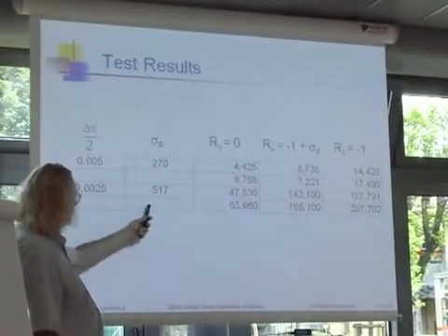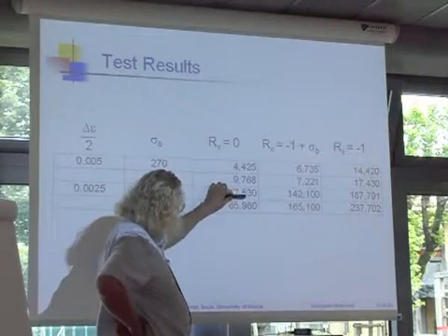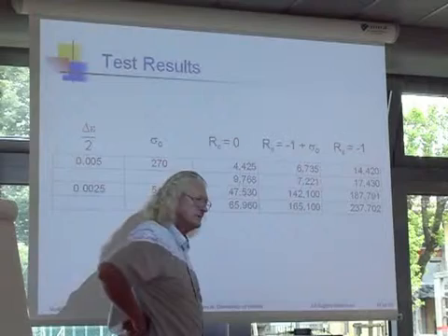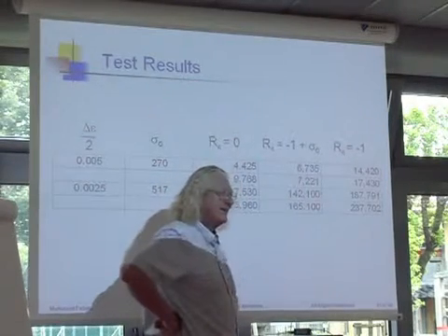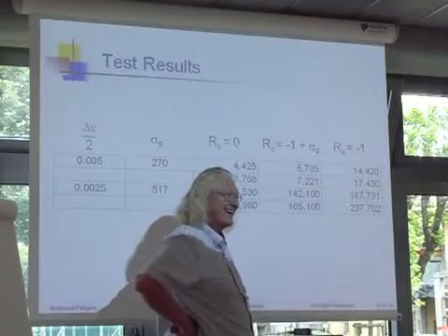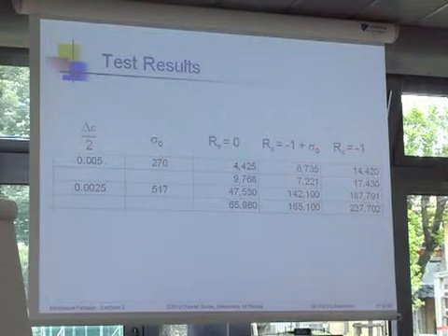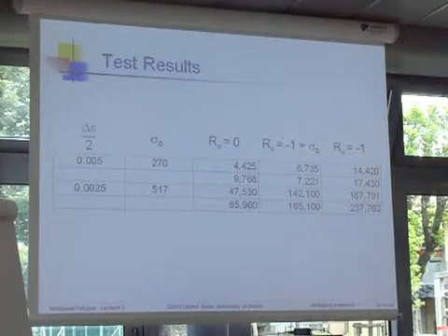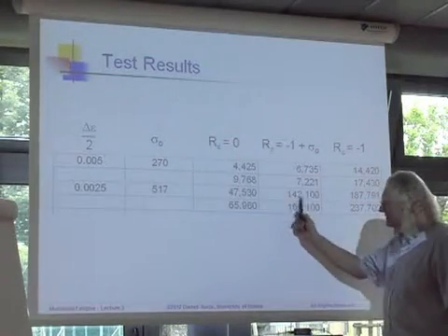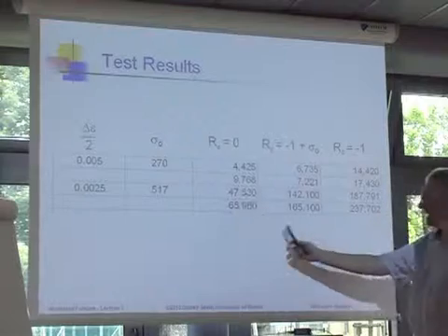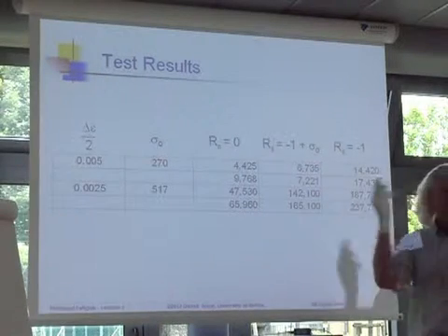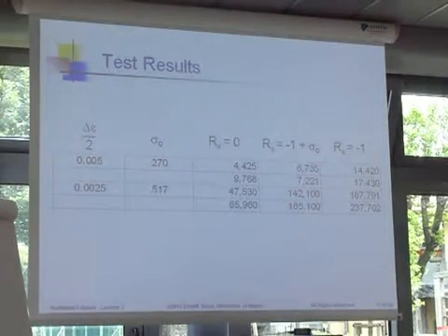So then I reduce the levels in half. Okay? And I put a really high mean stress. And look what happened. Okay, this is what happened for the one on the left. This is what happened to the one on the right. Very different. Very different. So something's wrong again. Because I thought, you know, these should have been the same as these, right? And instead, these are much more like these. Right? Much more like no effect. How could that be? Stresses are the same.